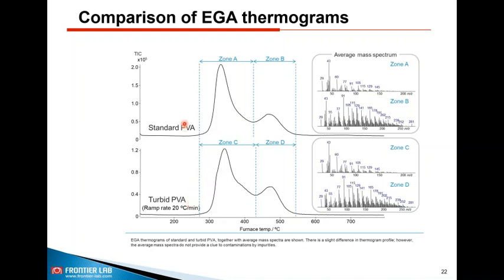Okay, the failed product and the QC pass product. We can see there is a small difference in the EGA thermogram in the second peak. So this is a bit larger. And similarly, when we look at the average mass spectrum, that also shows that difference, because there are some ions that you are seeing here which are not seen there. Okay, but the information is not sufficient to tell the clear reason for this turbidity. That means what we can say at this point, there is a difference which needs to be analyzed further.